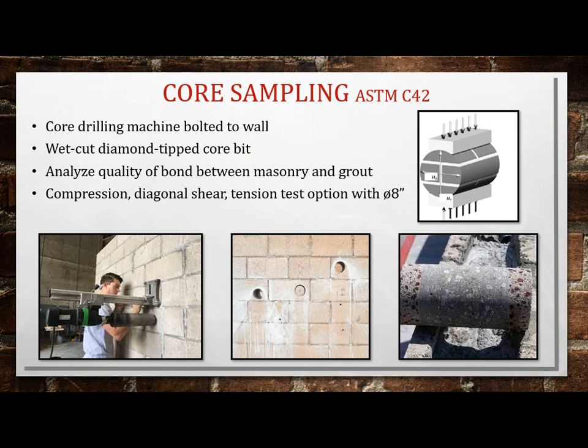So you can learn a lot from a core. You can determine the quality of the bond strength. You can look for voids. You can do a compression test on it. You can do a tension test on it. For masonry, the ASTM standard requires an 8-inch diameter core. And so you can actually get that core and rotate it and break it in different directions so you can determine the diagonal shear stress.